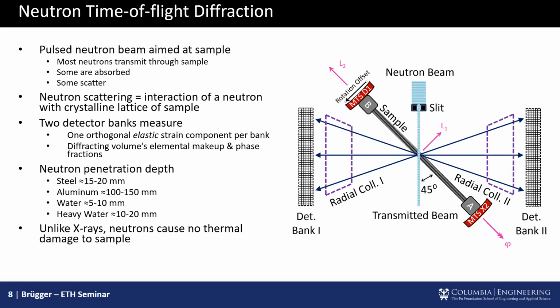So what we actually get from that is elastic strain, or at least a lattice parameter of our atomic spacing directly. And we actually get 2 scalars. So the most important takeaway here is that we're actually capable of measuring within a gauge volume, a little cube inside the cable, 2 elastic parameters of our crystalline structure. And now if you can imagine doing a D0 measurement, a baseline measurement somewhere, then we can also, between 2 stress states, actually get a relative strain. And we can do that inside a cable.